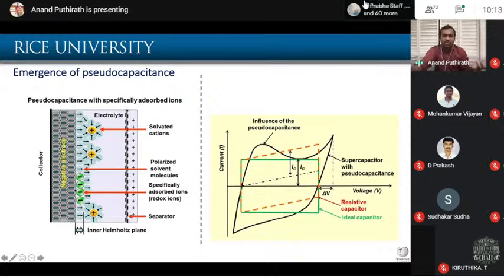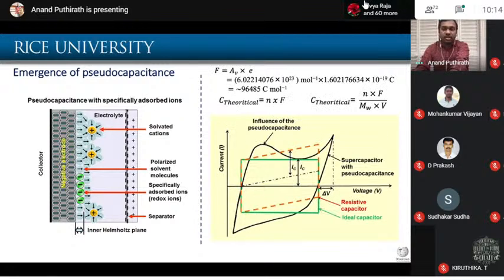And if you have adsorption, which happens for some particular types of electrodes, then we will say you have a pseudo capacitance also. So all these things can come together, which will increase the capacitance, but the kinetics is slightly lower for adsorption-type reactions, because you are adsorbing and releasing, so it will be slightly slow. So some sluggishness will be there, but it is still fast enough for better capacitance.